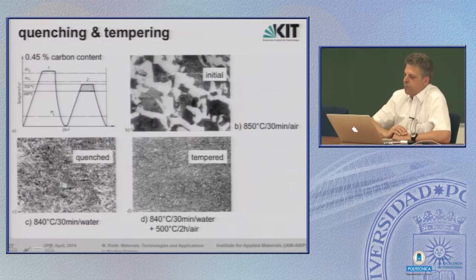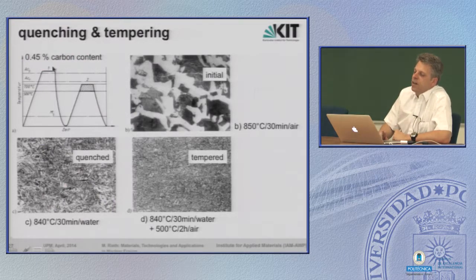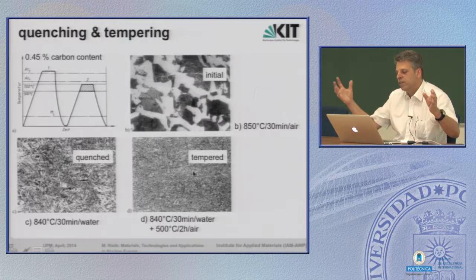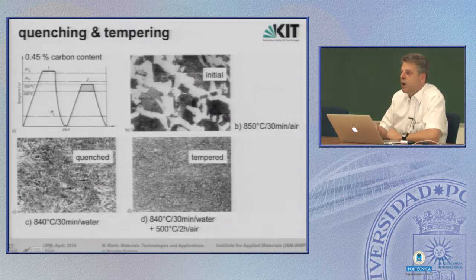And this is the basic mechanism, which is shown here again. First step is producing austenite with a high enough temperature. Then you quench down fast enough to produce this martensitic structure, followed on by a tempering period. It's a bit softened, but you see this is pearlite, which we started from. Then this is heated up to austenite and quenched down. You end up in a martensitic structure, and if you temper it, the carbon diffuses out of the lattice. It ends up on the grain boundaries, where else? And then it looks like that. So it still has a very fine microstructure, and this brings the good effect in these martensitic steels.